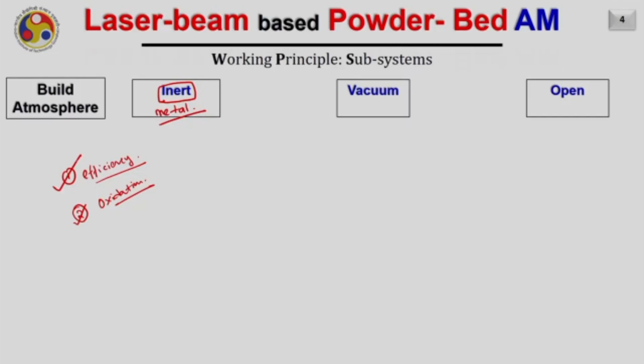Also, after completing the part, it is important that we recollect the unused powder appropriately and reuse it. But if the whole thing is happening in the open environment, it will be very difficult to collect the powder in the appropriate metallurgical state, because the adjacent powder, underneath or next to the part, gets a very high temperature, and in an open environment its metallurgical properties will definitely change. Therefore, it is wise to use an inert environment in the machine so that you can avoid the powder particles getting oxidized and can reuse them later. As a result, the efficiency of the process can be increased.